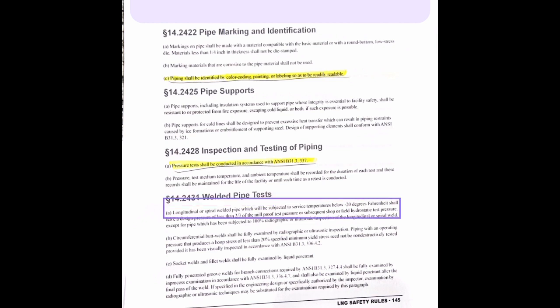A. A longitudinal or spiral welded pipe which will be subjected to service temperatures below minus 20 degrees Fahrenheit shall have a design pressure of less than 2/3 of the mill-proof test pressure or subsequent shop or field hydrostatic test pressure, except for pipe which has been subjected to 100% radiographic or ultrasonic inspection of the longitudinal or spiral weld. B. Circumferential butt welds shall be fully examined by radiographic or ultrasonic inspection. Piping with an operating pressure that produces a hoop stress of less than 20% specified minimum yield stress need not be non-destructively tested provided it has been visually inspected in accordance with ANSI B31.3, 336.4.2.